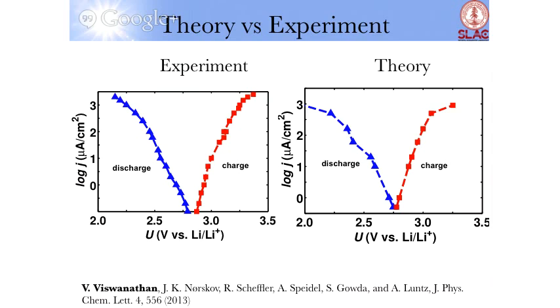And what's really interesting is the thermodynamic cycle efficiency is essentially the distance between the discharge and the charging curve. And so we essentially want to be off order 1 here. And so theory predicts a distance of about 0.3. Experimentally, they see a difference of about 0.4. So actually very interesting is that these two go back to this reversible point, which essentially shows that it's one electrochemical step that's rate determining.